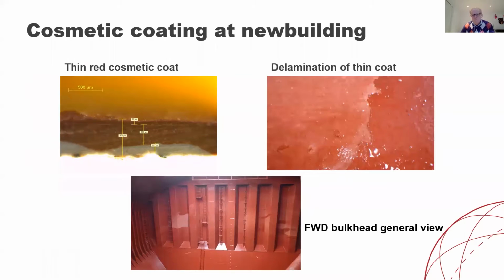And here I'm going to show you photos from some cases. The first one is cosmetic coating at a new building. As I already mentioned, the coating is typically a 2-coat system, and here you can see on the upper left-hand side the gray coating, which is 150 microns. The second coat is 299 microns, so you have overcoated here the second coat, but then you see on top there's about 70 microns of additional coating, which is this cosmetic coating that in this case a yard applied. And you see here that this would delaminate when carrying cargo, either because it wasn't fit for the job or it doesn't have good enough adhesion, and you will see how it looks in the bulkhead after peeling off.